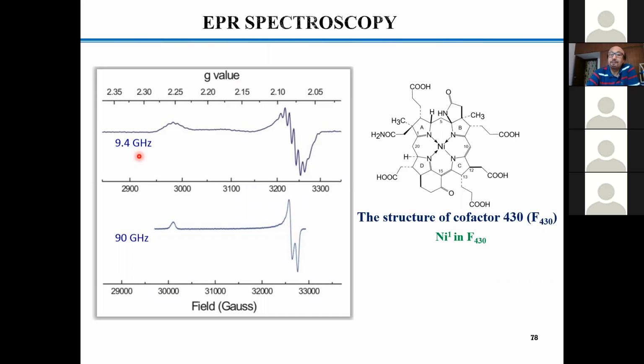and that is being observed in the normal X-band case. But if you go for a high field EPR situation, then at a particular temperature, you do not have this nitrogen hyperfine splitting in the beginning. Then you cannot get this splitting properly, and this tells you very clearly some kind of weak rhombic pattern. So weak rhombic pattern means X and Y are not identical over here in terms of ligand field interactions, which has now been resolved. Okay, and you could see that X and Y are being split over here. And if you go further lower in terms of temperature, you will start seeing all these hyperfine lines along the axis. Okay, so it will tell you much better information about the electronic structural form of your compound.